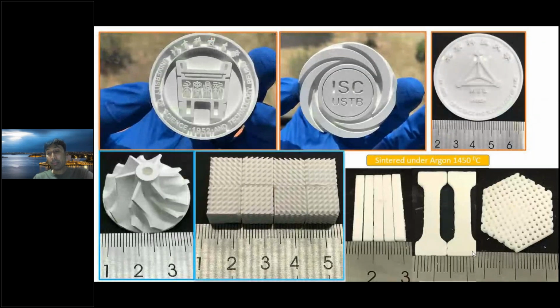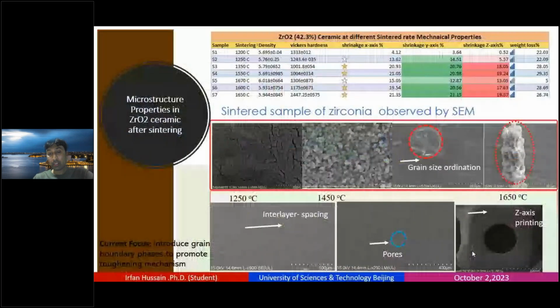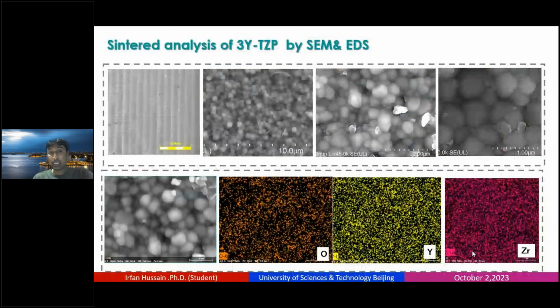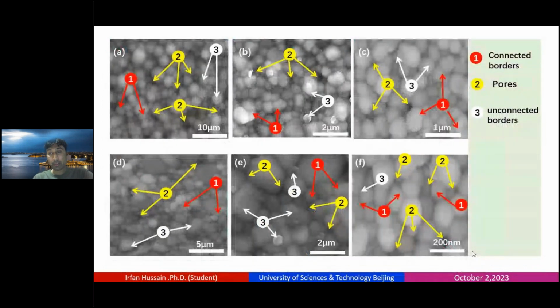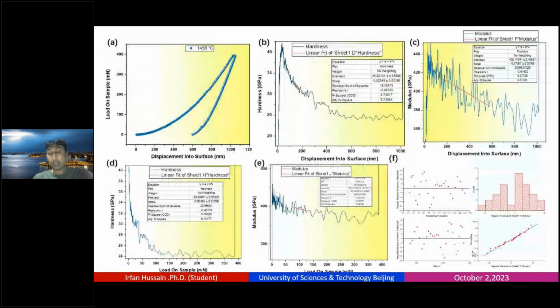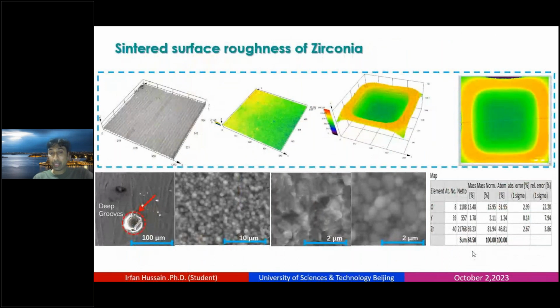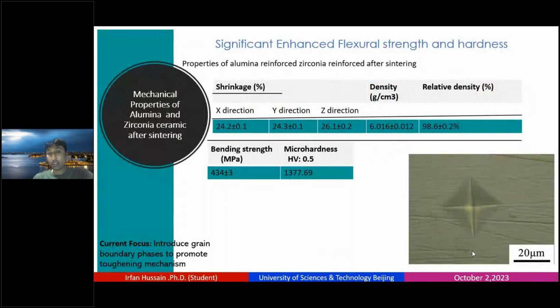So here are some complex shapes of my university monogram I have printed to ensure the precision and accuracy of the 3D printing. So here is the grain size of the zirconia ceramics 3YTZP. So here is the sintering analysis of 3YTZP, SEM EDX. You will see how dense the parts are in the microstructure at high sintering temperatures. Also here, the SEM microstructure shows connected borders, pores, unconnected borders, and some little pores. For the mechanical properties I have tested hardness, Young's modulus, and the linear fit. After that I observed the surface roughness of the specimen and the significantly enhanced flexural strength of the 3YTZP zirconia.